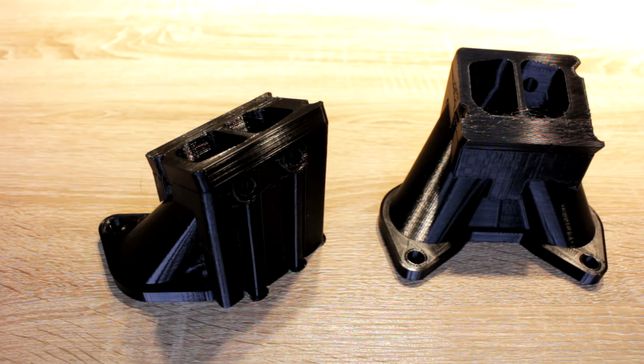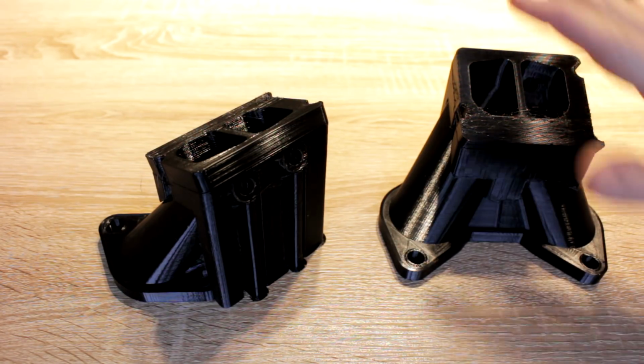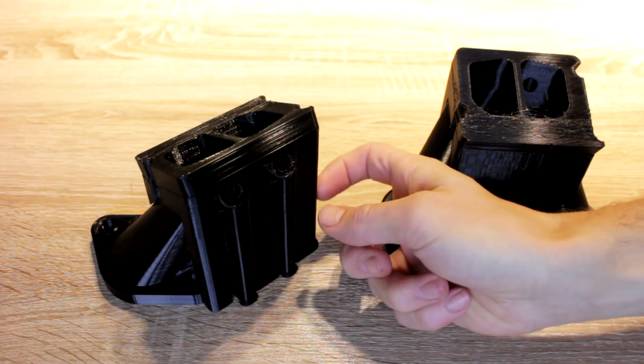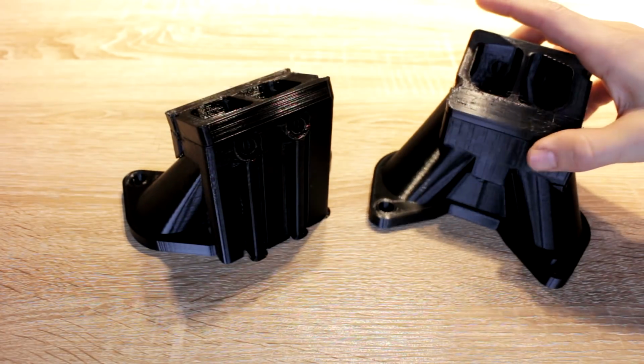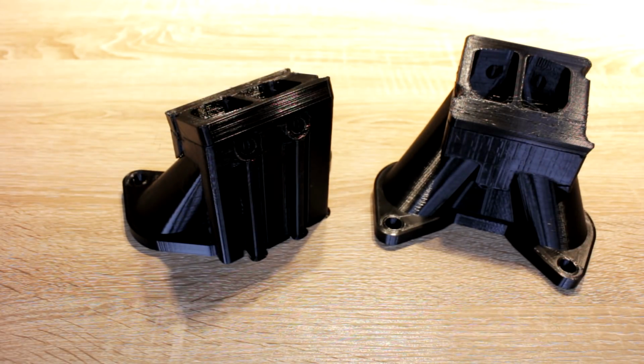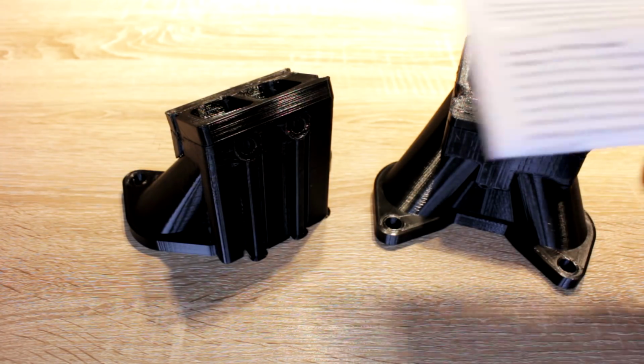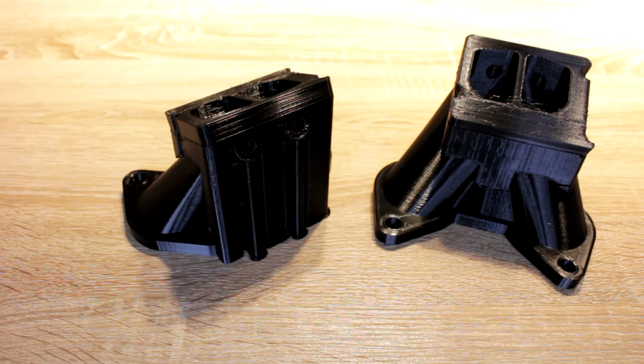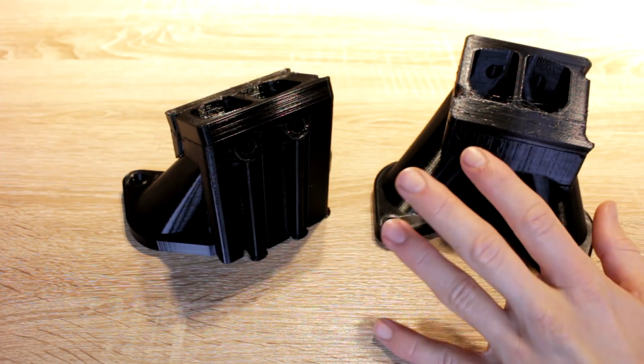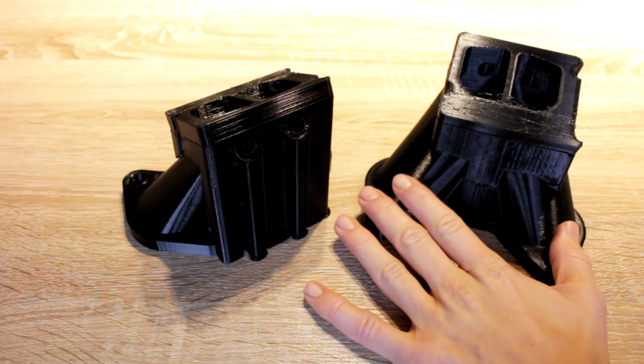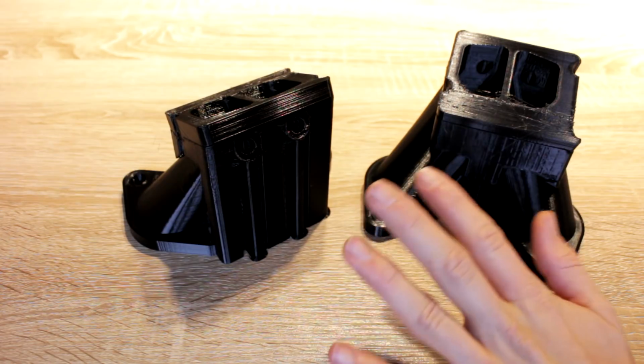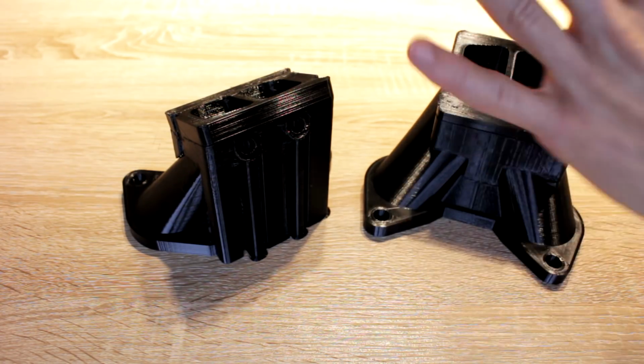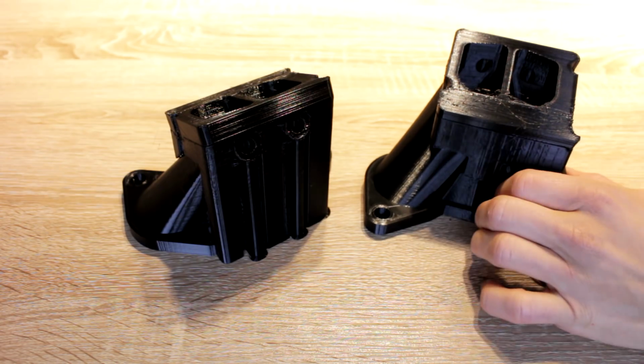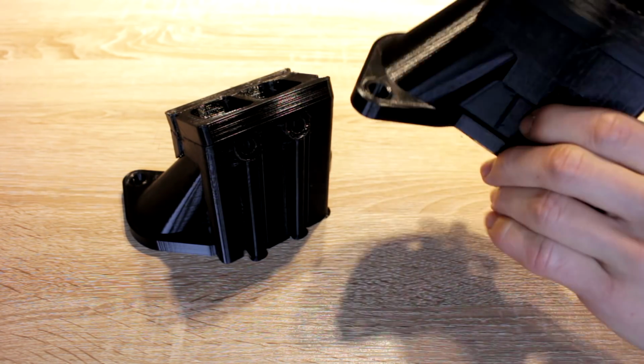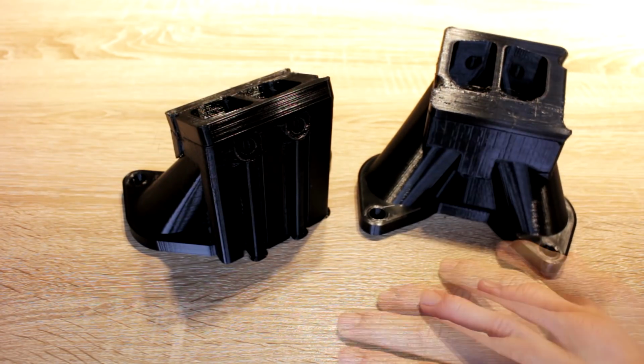Both of the intake manifolds have been printed with 3DK top filament. There wasn't any warping this time, so both manifolds are completely printed. You can see that I left the support material on there, and that's because we need to do some post-processing. I have the instructions here from 3DK, and we have to post-process this. This is like a sintering step, to put them in a normal convection oven at 110 degrees centigrade, and we have to leave them in for, it all depends a bit on the wall thickness. So this is a very big object with heavy walls, so we're going to leave this in for a couple of hours. We're preheating the oven now.